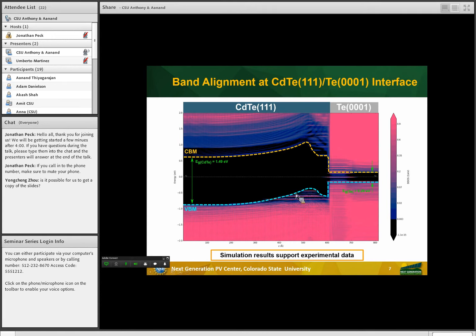We right away notice that there are electronic states that exist within the tellurium band gap. We also see a pickup in the valence band due to higher hole concentration in the CdTe layer. And the model also suggests some type of upward band bending in the conduction band. All of these effects in the DFT model are beneficial to the CdTe device properties and may explain why, experimentally, we see such an improvement in the tellurium back contact.